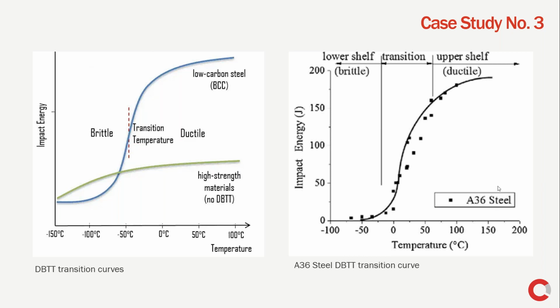In a case like here on the right, which is the A36 steel, a very common steel used for construction of tanks and other equipment, we have a transition temperature that is roughly around 10 Celsius or so. What that says is we can't use steels like these on equipment that is subject to flexural loads or extreme flexural loads or impact or other applications where the material should have a transition temperature much lower. And in this case, that's pretty much what could have happened.